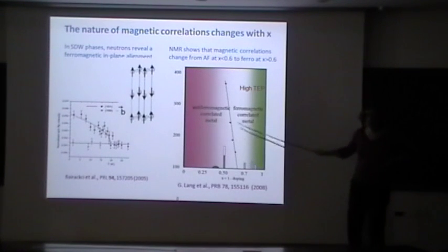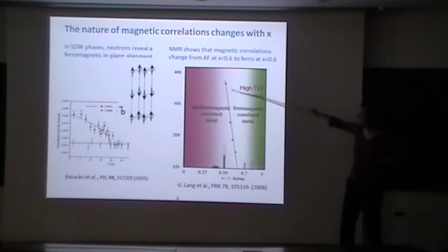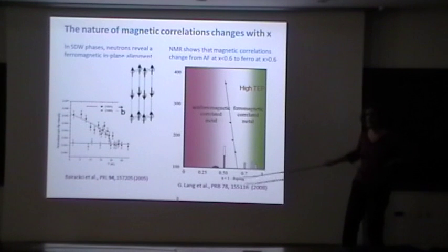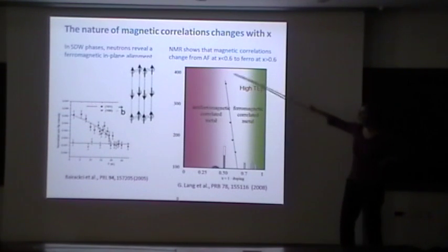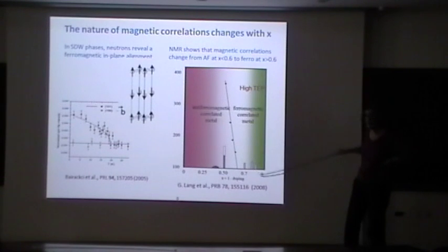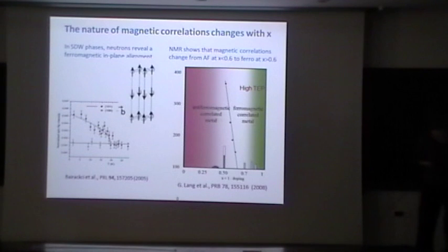So in fact, you have two different types of metals. You should look at them with different types of correlation, with some kind of boundary here around 0.6. If you look at these papers, they discuss a little of what you were suggesting, that maybe you have this Curie-Weiss temperature which is just shifting with x and which will be at a much higher temperature. This is actually the maximum of the susceptibility that you can measure. I don't think they measure up to very high temperature to really know if it's decreasing again or not. But now I will focus on this part of the phase diagram where you have all these anomalies of spin and charge: strong ferromagnetic correlations with this Curie-Weiss susceptibility, and also high thermopower.